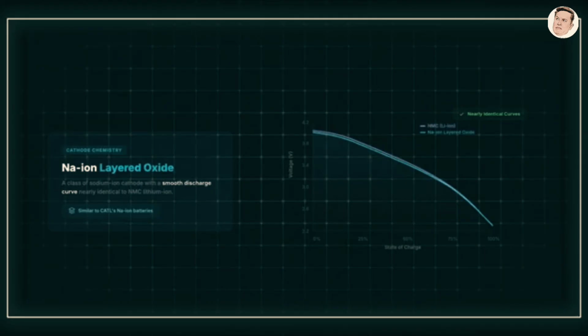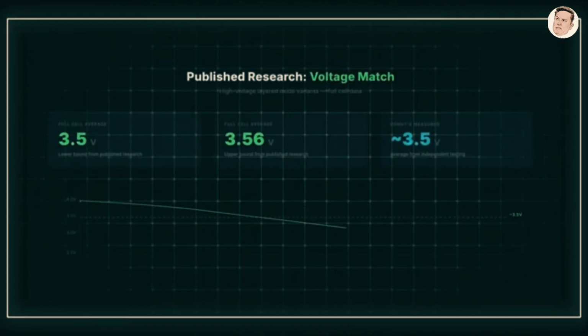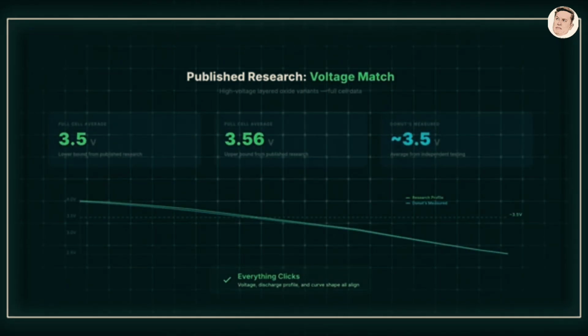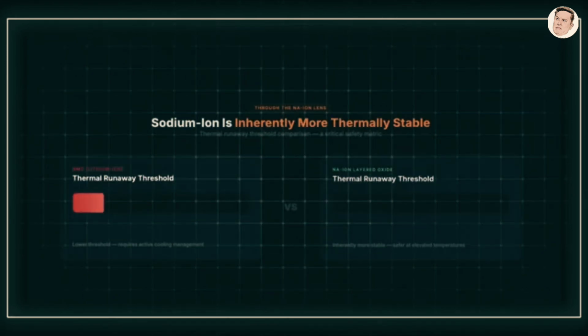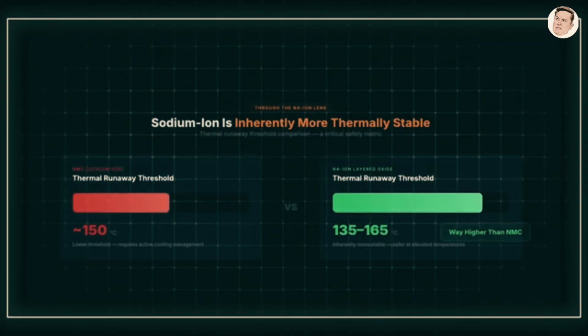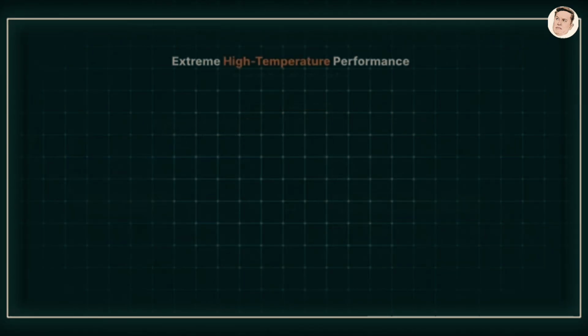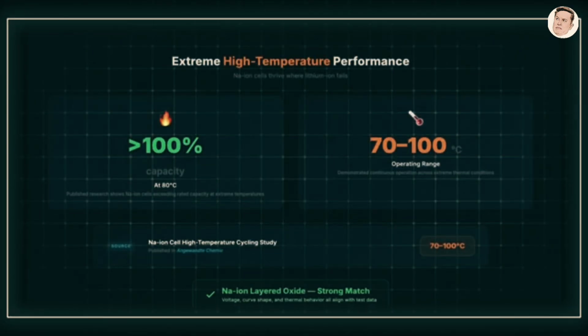Now think about what that means. If this was a conventional lithium-ion cell with standard liquid electrolyte, a pouch breach at 100 degrees Celsius would be dangerous. The organic solvents in lithium-ion electrolytes are flammable. DMC is one of the most common ones. It boils at 90 degrees Celsius. So now you have flammable vapors, oxygen in the air, and 100 degree temperatures. That's the fire triangle. The cell would probably catch fire, melt down, or at minimum be completely destroyed.